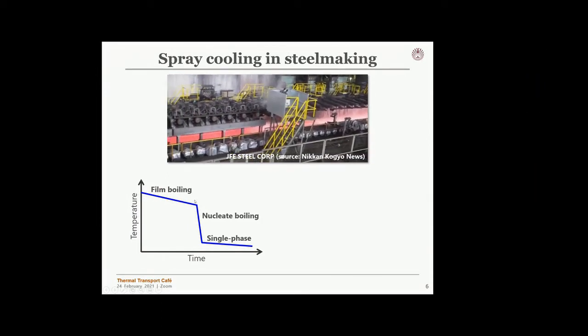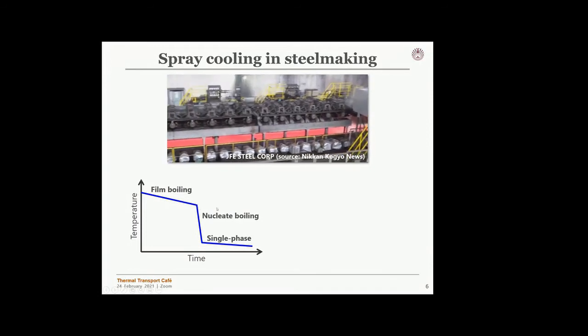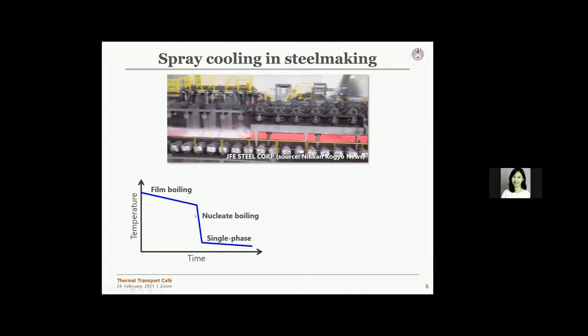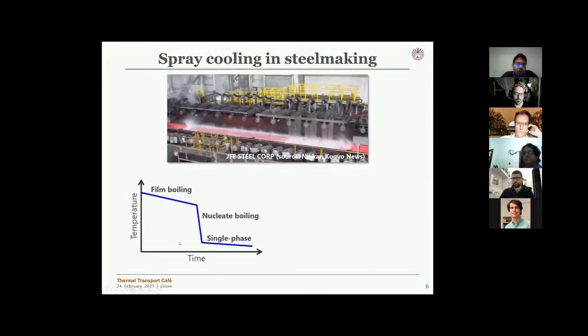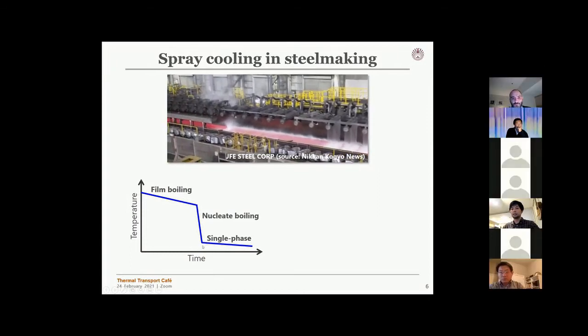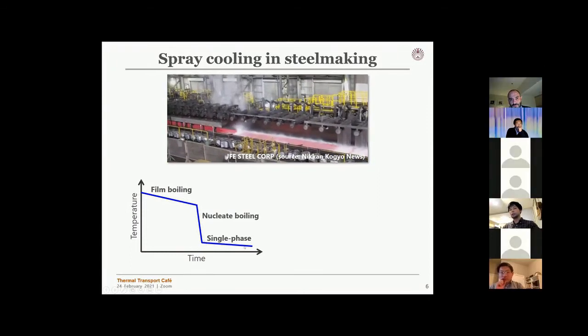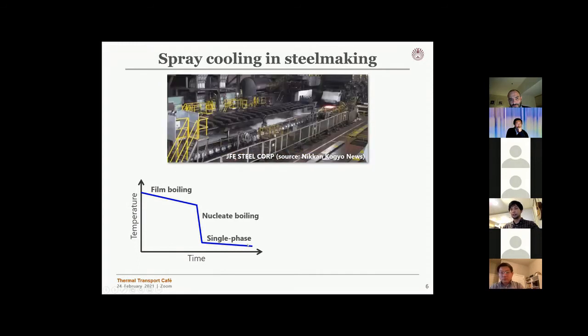At some point you will have a transition from film boiling to nucleate boiling. When you have nucleate boiling, the temperature drops rapidly to the saturation temperature, which is about 100 degrees Celsius, and then it goes to the single phase regime.